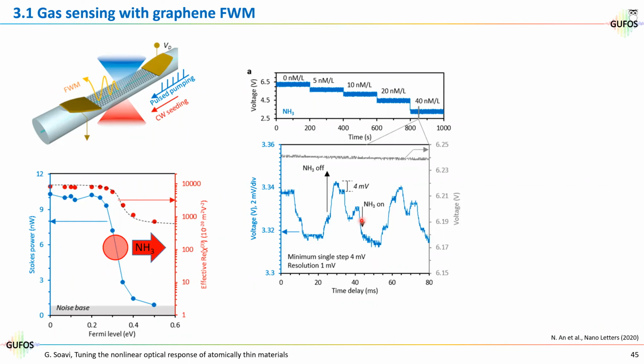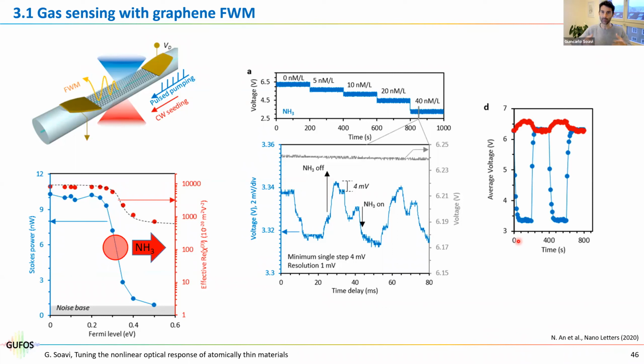And you have these, let's say, quantized steps that are in the order of 4 millivolt. And if you now do the math, it turns out that these quantized steps of 4 millivolt correspond to adsorption and desorption of individual gas molecules. So this device is so sensitive that we can look at individual molecules of ammonia that get attached or detached from the graphene layer. And another advantage of this device is that, of course, if you keep flowing ammonia, at some point you will saturate the device because you will have the full surface of graphene covered by ammonia.